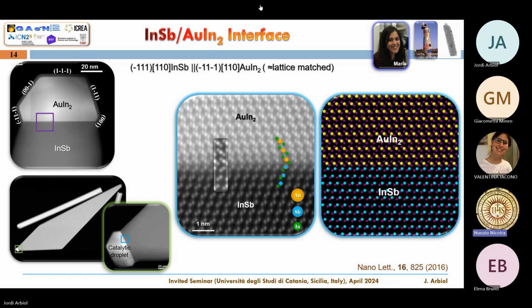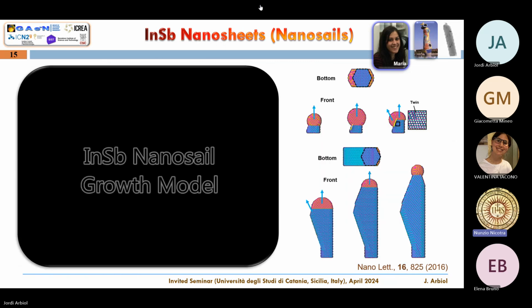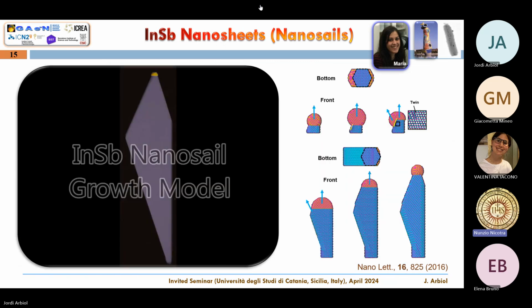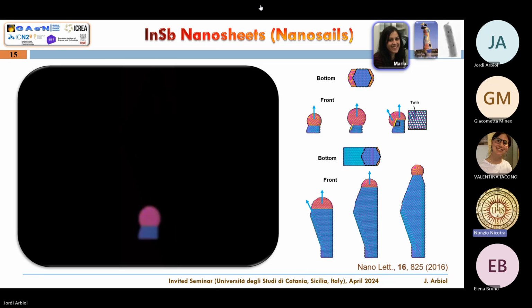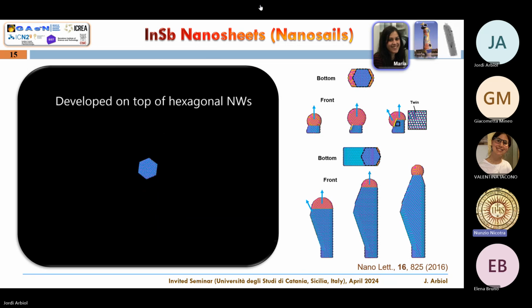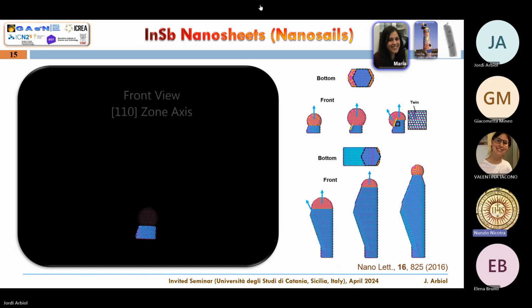So what is going on during the growth? And I will try to show you with this model. So at the beginning, this is the final nanocell, but at the beginning, what you have is the indium arsenide, and then this is the indium and gold droplet that you have on top. This is the cross-section of the nanowire, perfectly hexagonal, with six 110 facets that are unpolar. And then suddenly, when you are starting to add the antimony, this droplet grows.